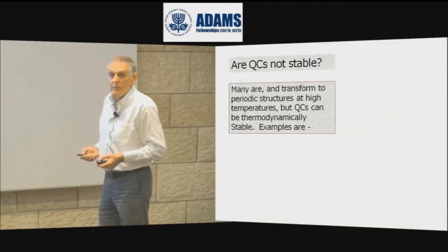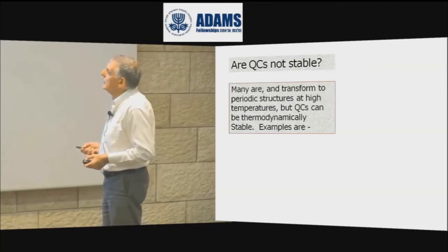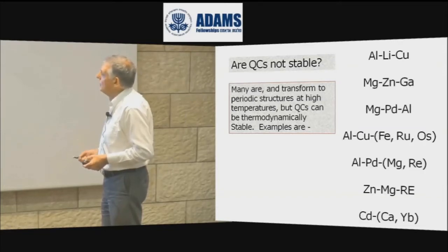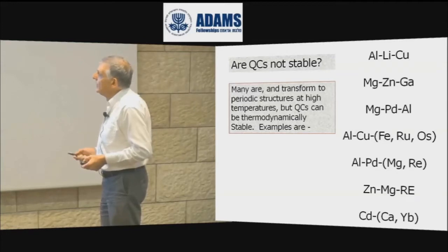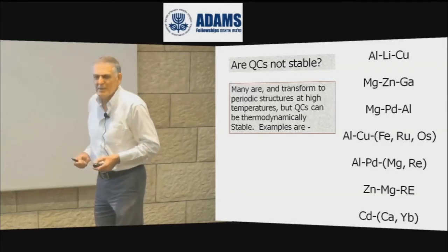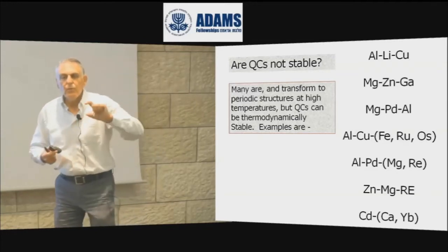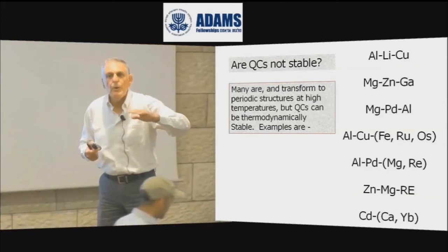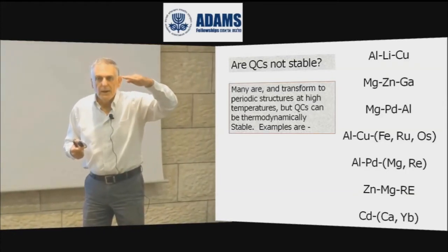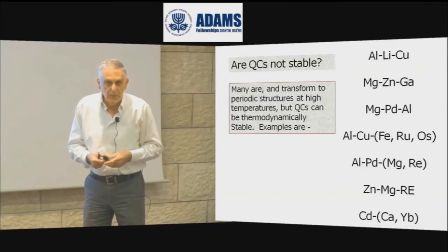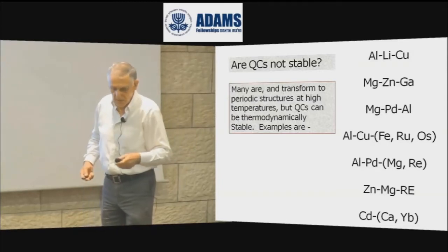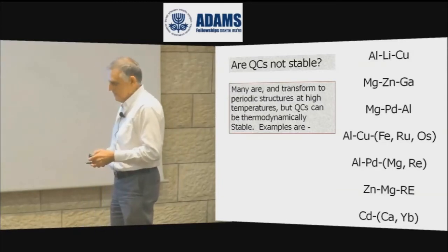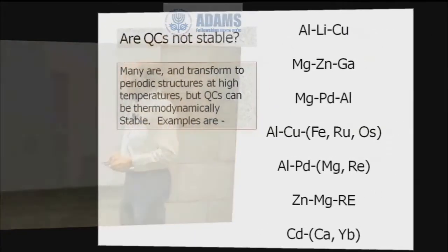Are they not stable? Many are stable, and some transform to periodic structure at temperature. But quasi-periodic crystals can be thermodynamically stable, and here are a few examples of thermodynamically stable ones. But also the ones that are not stable, what does it mean not stable? They transform into periodic crystals when you heat them up to 400 degrees C. But at room temperature, okay, no problem. So this is not the reason that they were not discovered before me.